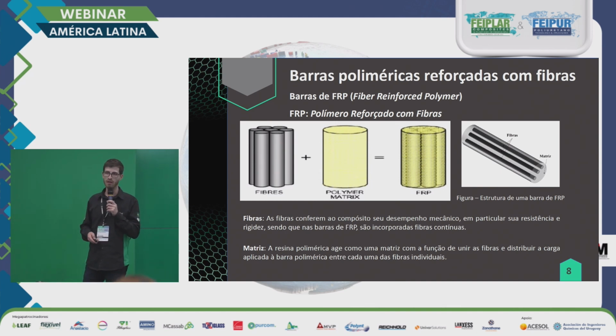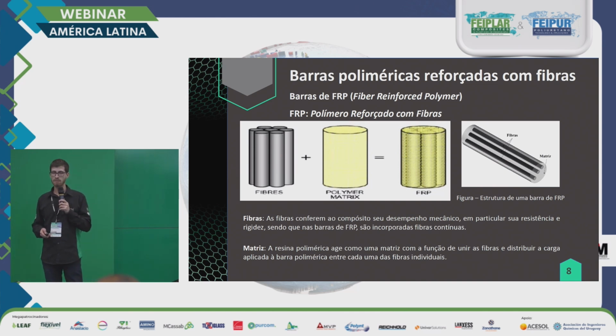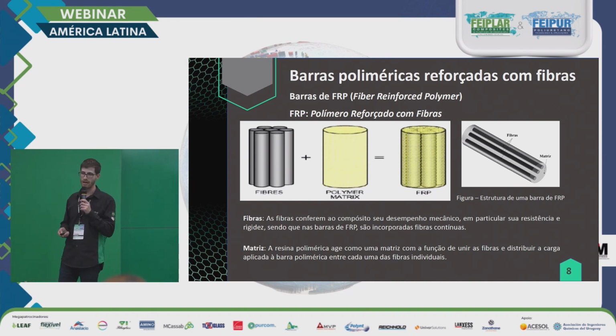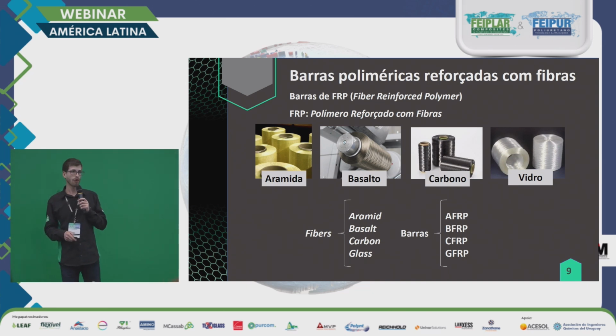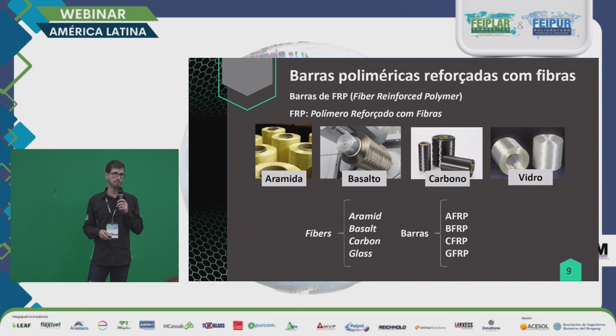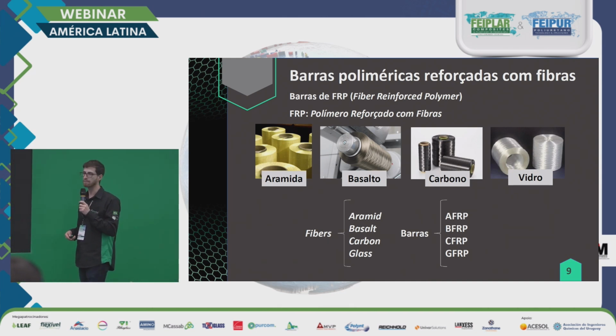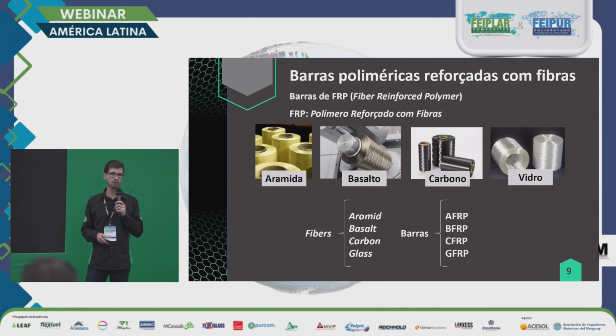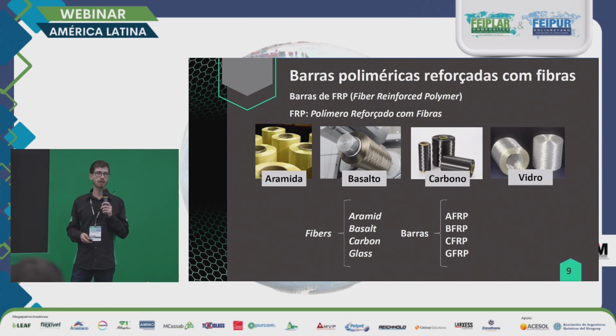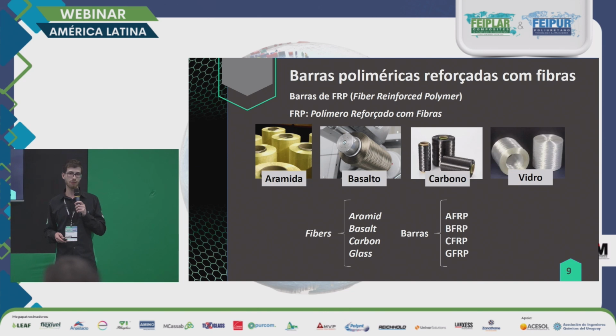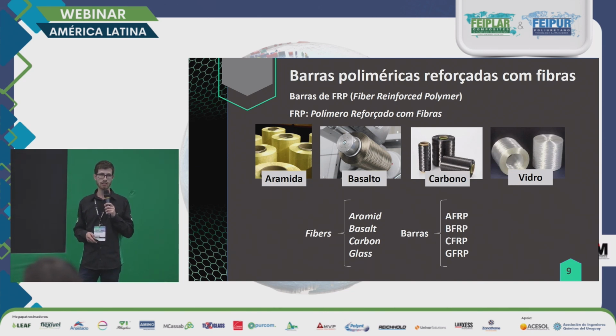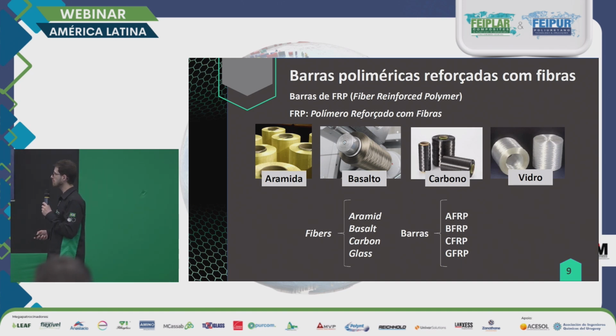Here you see the physical structure. You have the core with the fibers, and we have different types of fibers and resin. Fibers are meant to resist, to give mechanical properties to the rebar, and resin absorbs stress and transfers this to individual fibers. As I mentioned, we have different types of fiber available in the market. So we have glass fibers, carbon, aramid or basalt. The main fiber used in the market because of its cost performance ratio is glass fiber. Composites with glass fiber have strength that is 2 times that of steel.